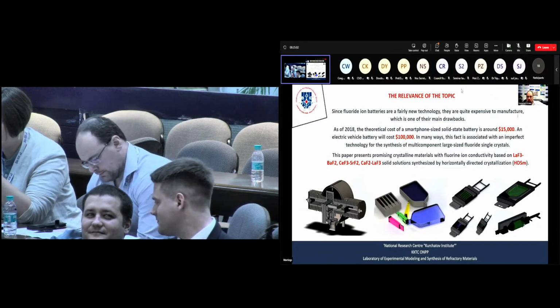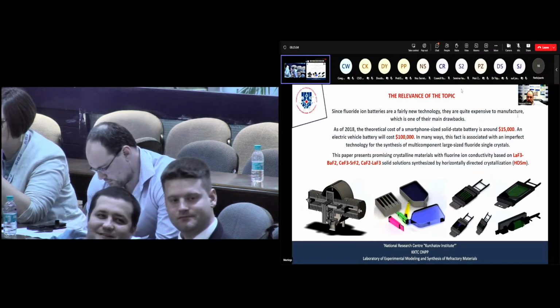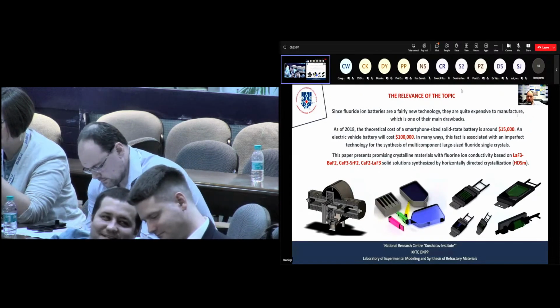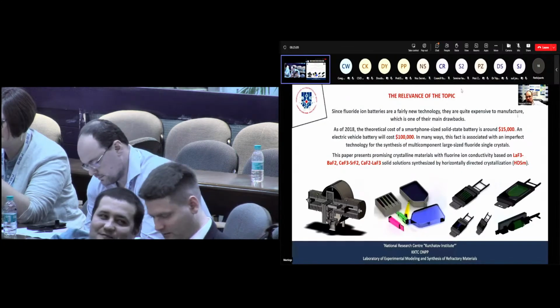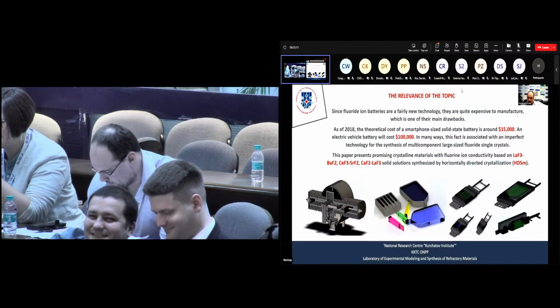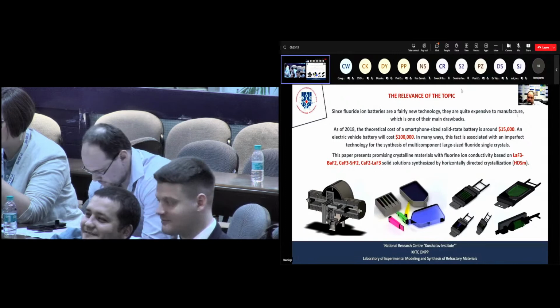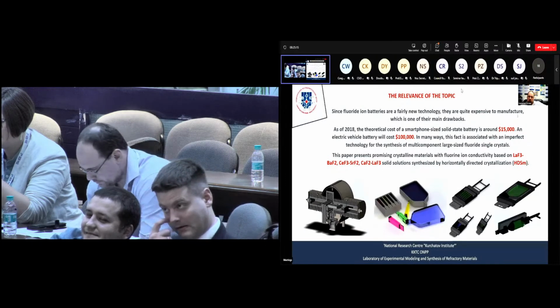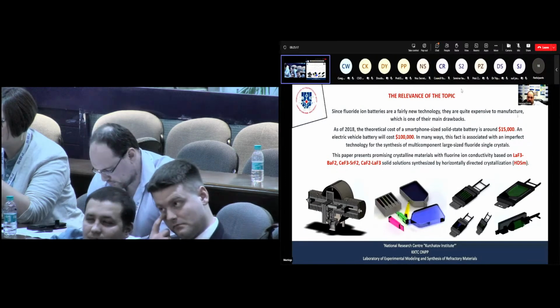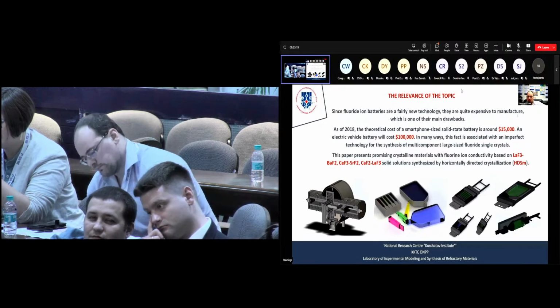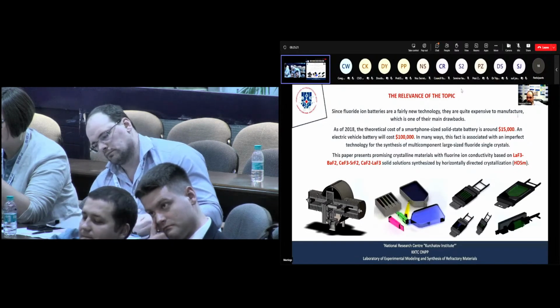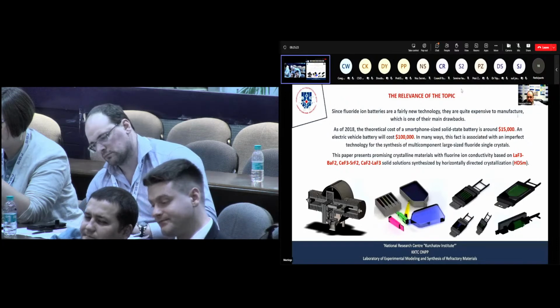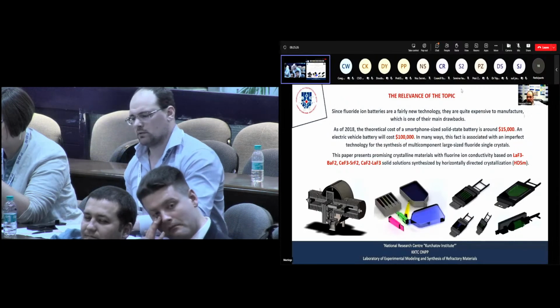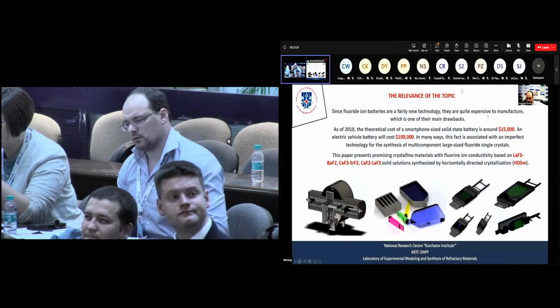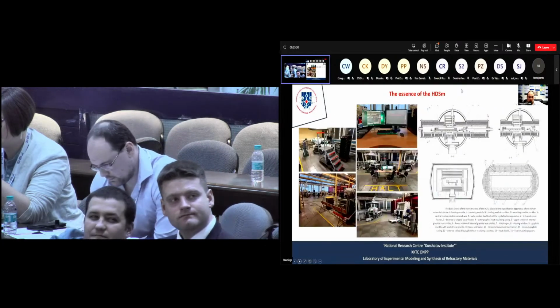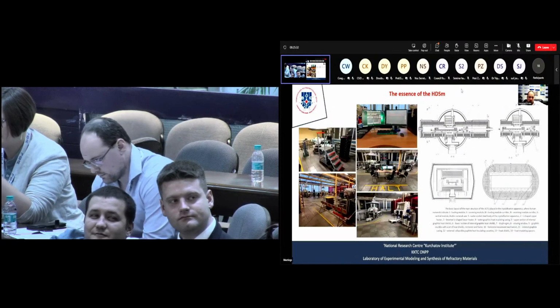This paper presents promising, well-known crystalline materials with fluoride ion conductivity based on lanthanum barium fluoride, cerium strontium fluoride, and calcium lanthanum fluoride solid solution crystals synthesized by horizontally directed crystallization. What is the HDSM method? The essence of the method is as follows.